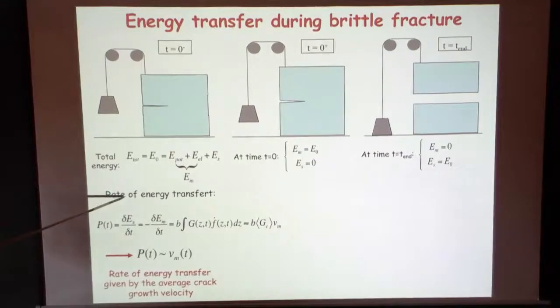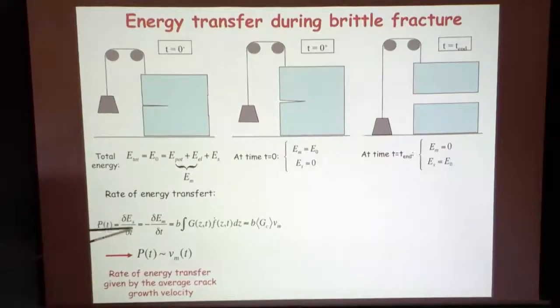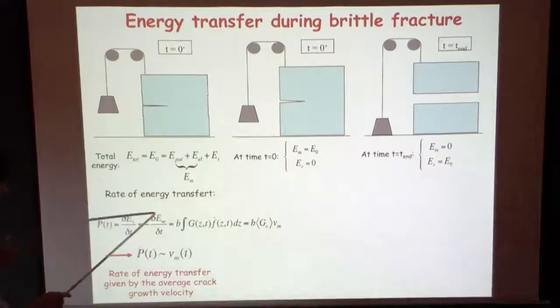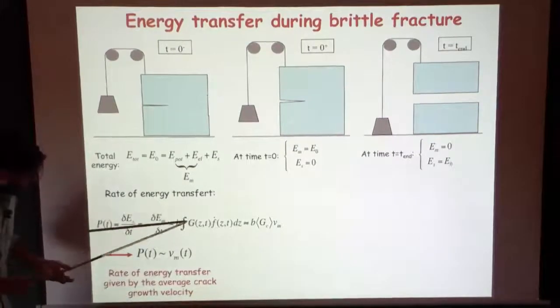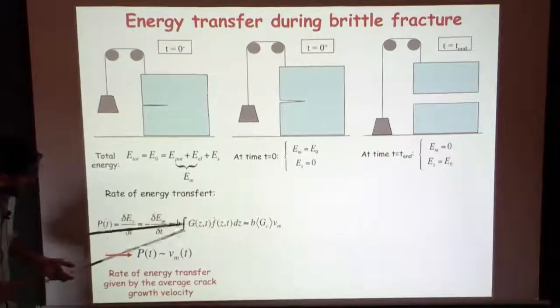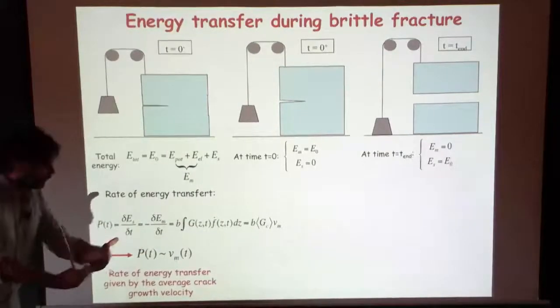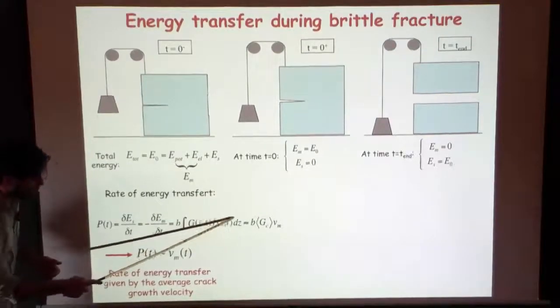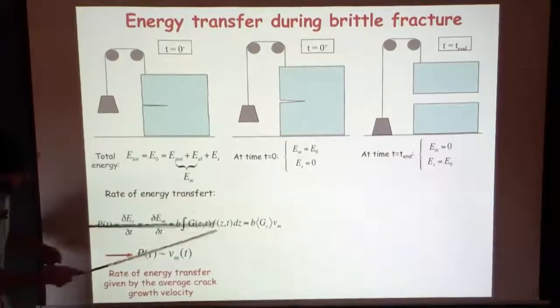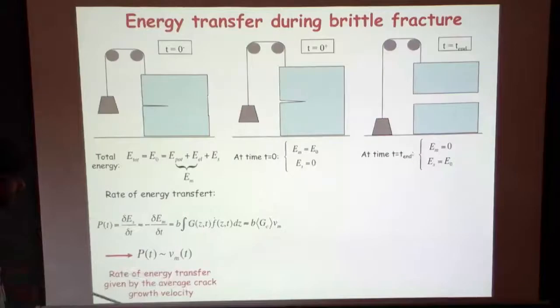First of all, I need to define this quantity, the rate of energy transfer, which we already somehow discussed previously. It's the power of energy dissipated in fracture or in surface energy. It's also the opposite of the rate of variation versus time of the mechanical energy. And we introduced this quantity before because it's related to the energy release rate, G. So this definition is straightforward. It is G times delta EM, that is G times the surface crossed by my crack. So it's G times F dot times delta T times dZ, integrated along the front. And the delta T, you get rid of the delta T. There is a B showing up from the definition of G.